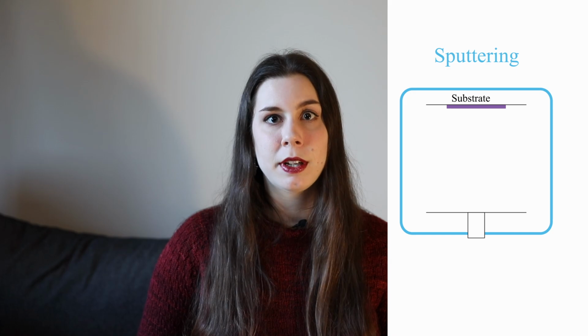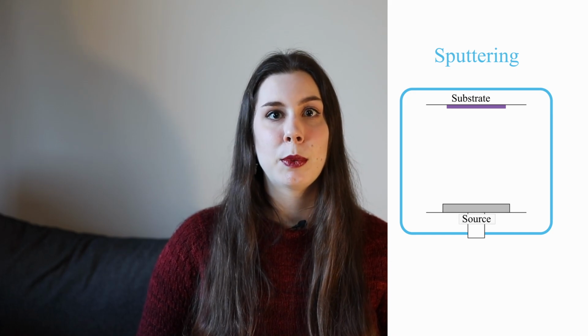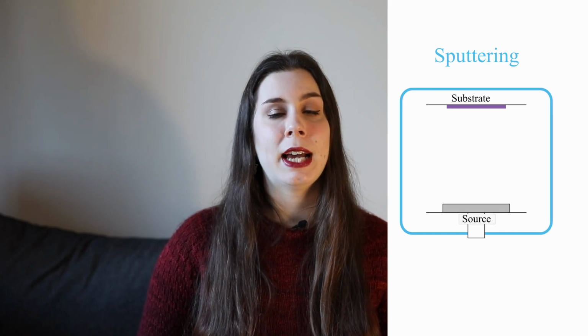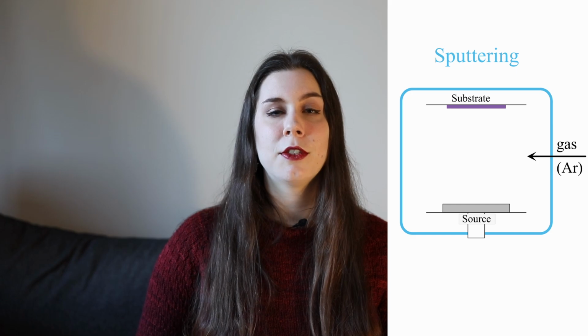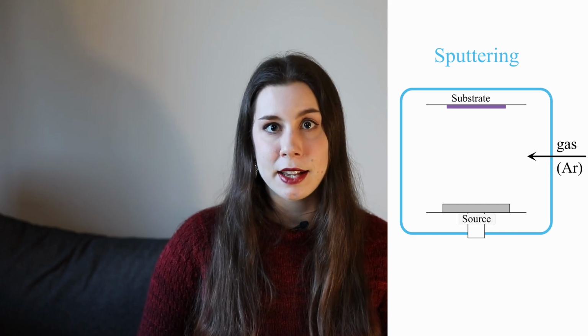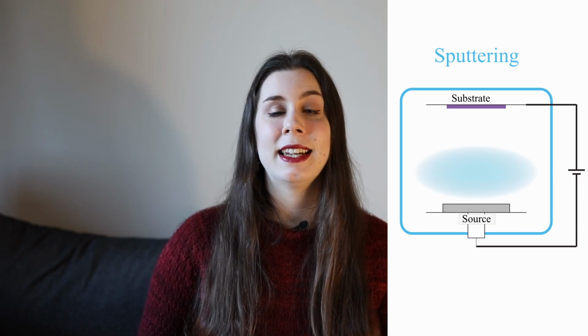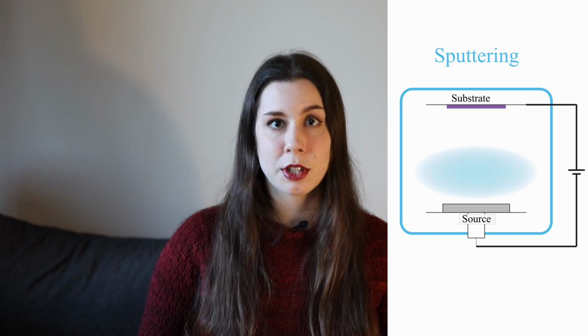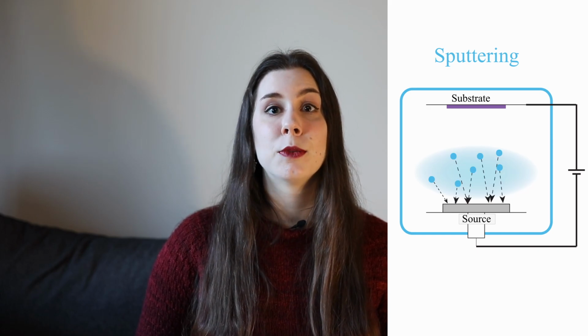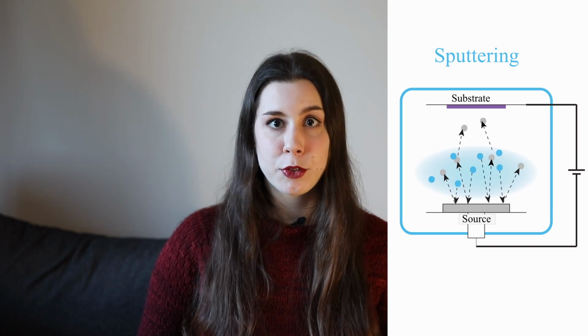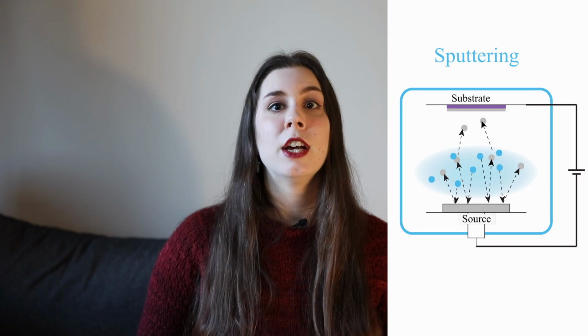There are many different ways of depositing a metallic film onto a substrate. In this step, we'll use a technique called sputtering, where we'll place our substrate into a vacuum chamber facing a source of the material we want to deposit, which in this case will be aluminium. The chamber is then flooded by a heavy but non-reactive gas, and the plasma of this gas is then ignited by applying a voltage across the chamber. The plasma ions bombard the source, knocking out atoms from it, which then land on the substrate, forming a thin